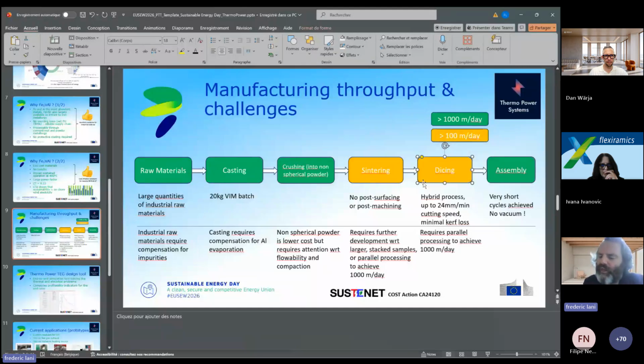If you want to achieve 1,000 modules per day, we need to process dicing in parallel with multiple machines. And then regarding the assembly, this is brazing in this case, we have been able to achieve very short cycles and avoid having vacuum. Of course, avoiding vacuum and having short cycles is very good for our material, but might not be convenient for other materials. But this is our manufacturing chain as is.